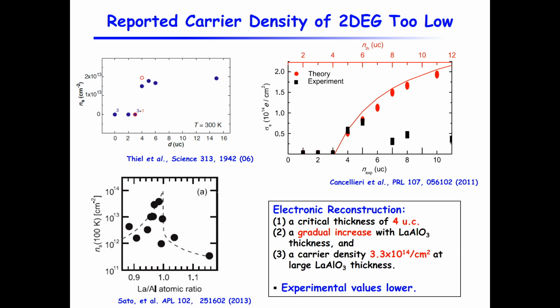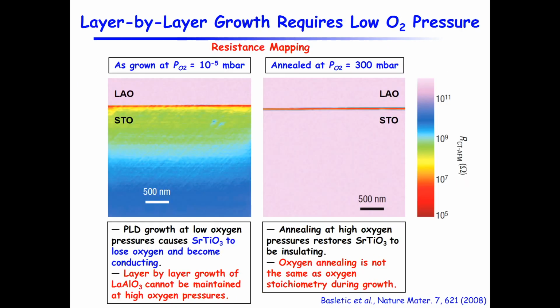This is a work that actually studied the change of stoichiometry in the lanthanum layer. They do see a dependence on composition, but all these values are still off from what people would expect, 3.3 times 10 to the 14th. So the problem is that when people grow lanthanum aluminate layers, they cannot grow the materials at high oxygen pressure because they will not be able to grow the film layer by layer. Because of that, people have to grow the lanthanum aluminate film at low oxygen pressure. And it is known that strontium titanate loses oxygen very easily.